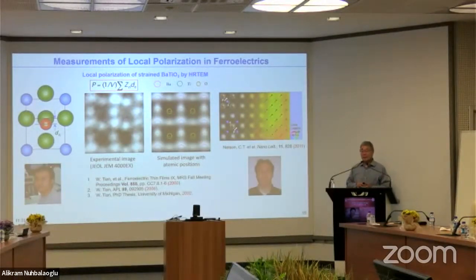The exploration of the atomic scale properties of ferroelectrics has been going on for decades. I just want to highlight a few things that we did earlier. At that time, atomic scale measurement of polarization was not available, so we developed it using quantitative TEM methods. At that time there was no aberration-corrected TEM, but we could use a quantitative method involving atomic structure simulation and image simulation to model the system, and then get the precise position of each element in the crystalline material using the coordinates determined by quantitative TEM.